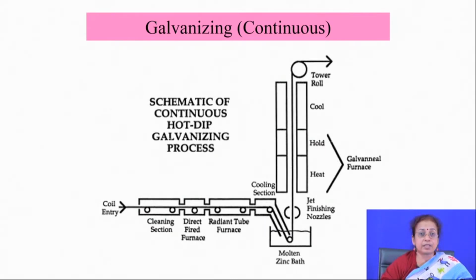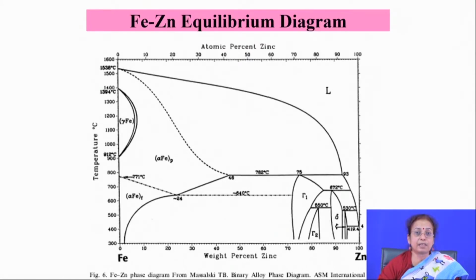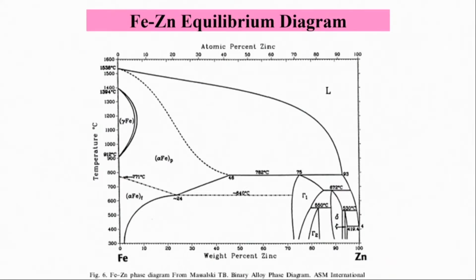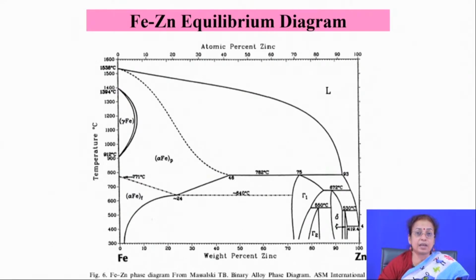So, it is a very interesting way of depositing on the surface of metallic materials, which can offer very good corrosion resistance property. But one of the biggest disadvantages is that, though the interface is strong, if you see the interface carefully, you will find that at the interface there are several intermetallic layers formed. Those intermetallics are highly brittle in nature. That brittleness of the intermetallics in the iron zinc system creates problems for its applications.